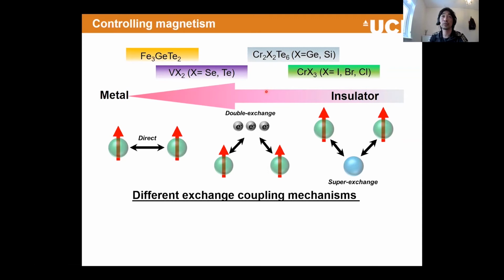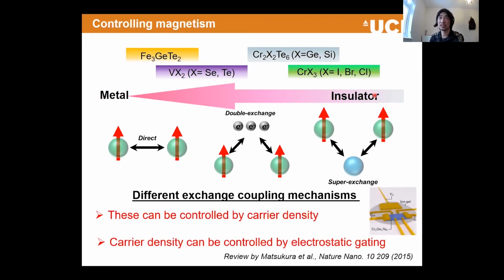And also, if you are fully doped and the Fermi level is within the band, then we tend to believe that the description of an itinerant material, a band-like picture, is suitable, and we can discuss the Stoner criteria and also Pauli paramagnetism. So what we can do with these materials is change the conductivity from insulator to metal, and the question is, how do we control this magnetic exchange interaction? That's the motivation of our latest work.